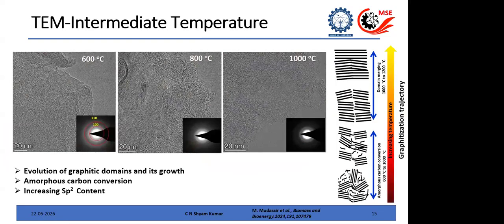Now, with Raman, we can understand how it is becoming carbon and how the graphitic content is increasing, but you also need some more careful look or high resolution imaging techniques to look into the evolution of the microstructure. So this is TEM, and you can see from 600 to 1000 the evolution from a disordered carbon to small graphitic flakes, which is happening at 1000 degrees Celsius. So now you know that there is a higher amount of sp2 at 1000 degrees Celsius, and the sample is almost kind of a flaky graphitic structure.